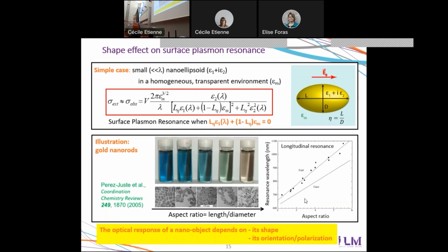So you have a concrete example of this here with solutions of gold nanorods. You can see electron microscopy images of the objects here. They are more and more elongated along this direction. And as you see clearly, their color changes. And here are the corresponding resonance wavelengths. For not too elongated particles, it is still in the visible range here. But as the particle is more and more elongated, the resonance belongs to the infrared domain.